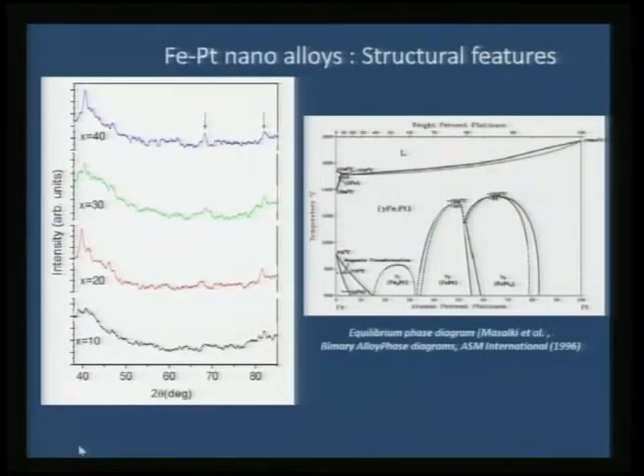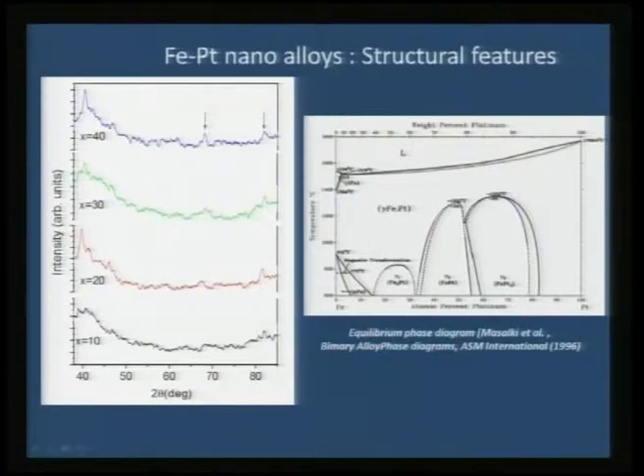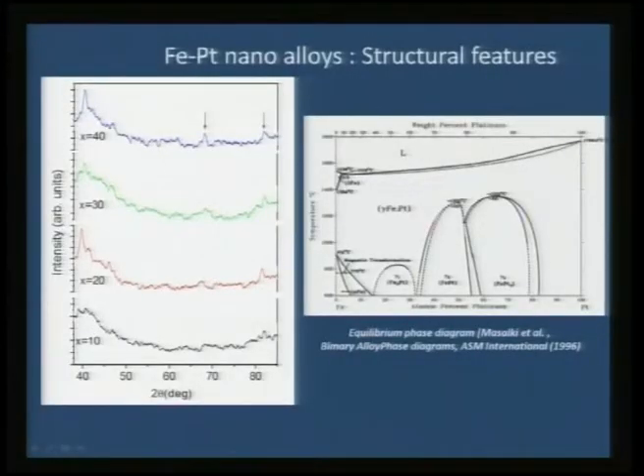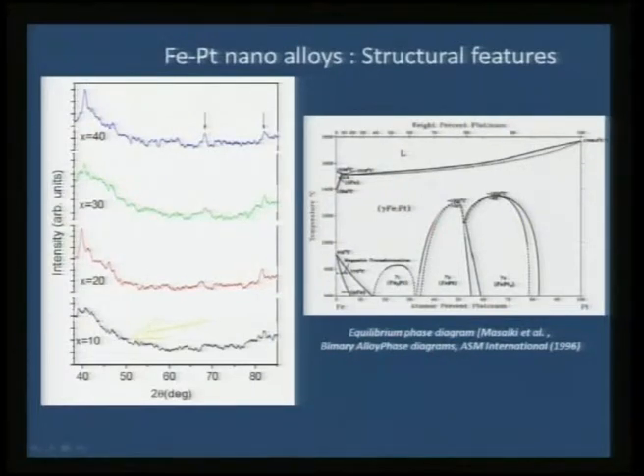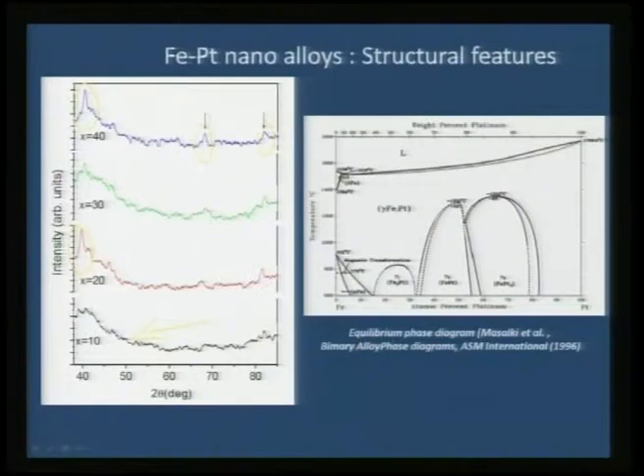Looking at the X-ray diffraction pattern, the alloy is not absolutely amorphous. With more and more platinum, some crystallization process occurs. Without platinum, it shows a typical amorphous phase from the XRD pattern, and prominent peaks emerge due to platinum as the ratio increases to 40 percent.